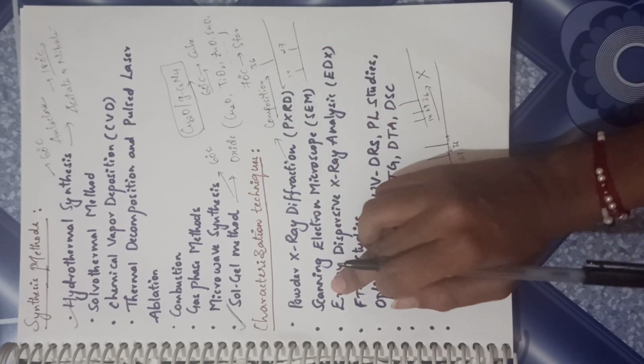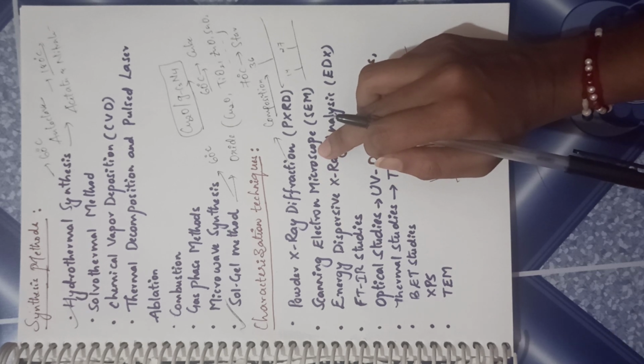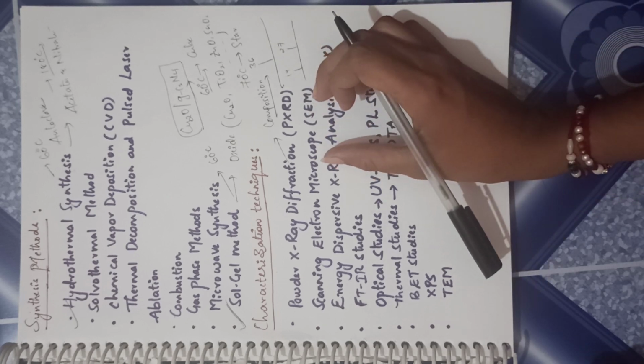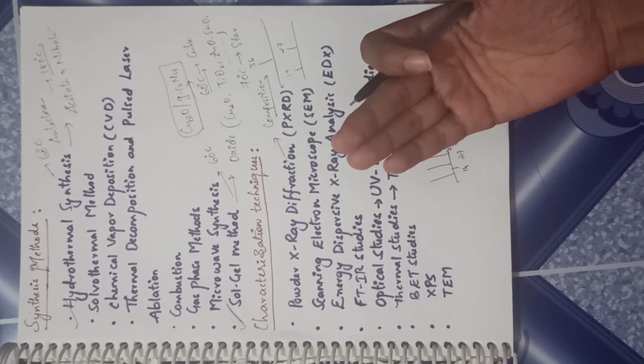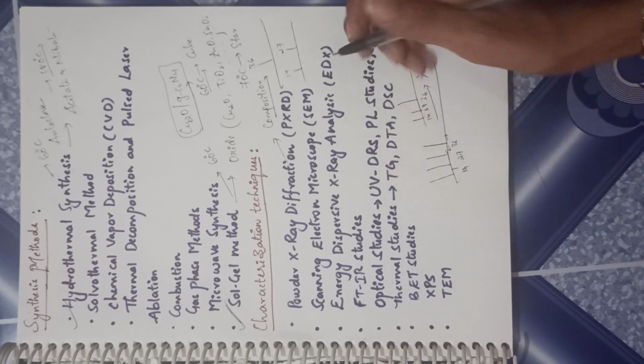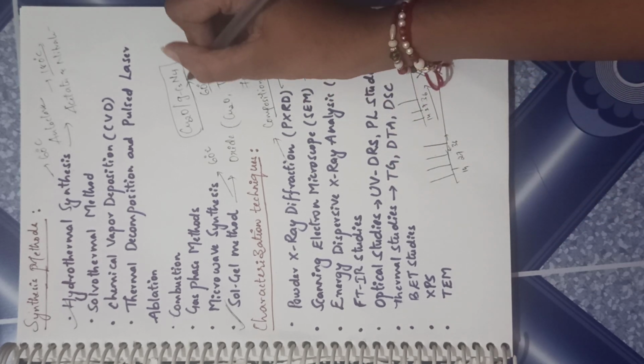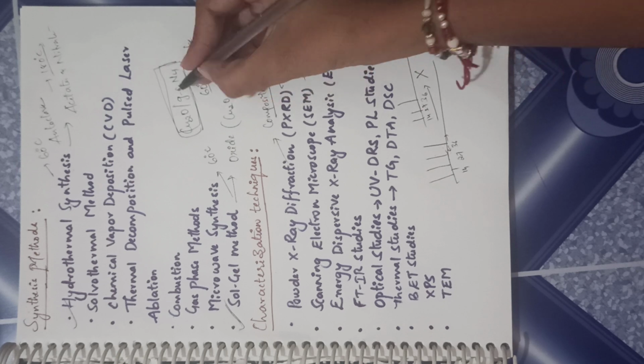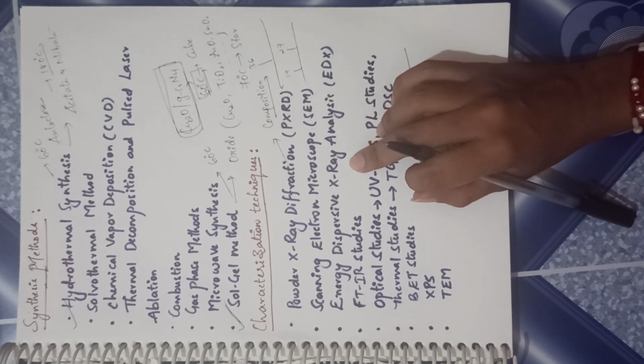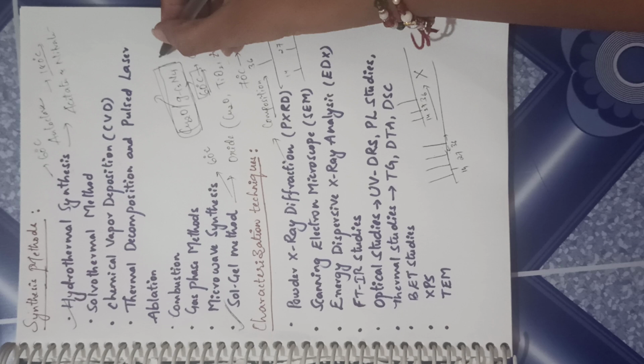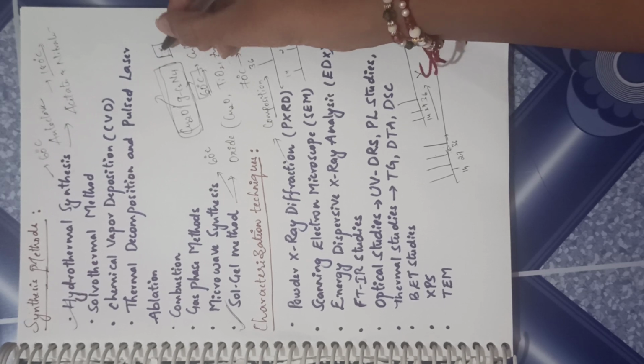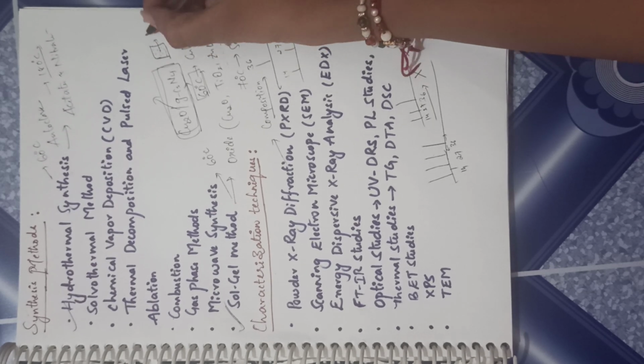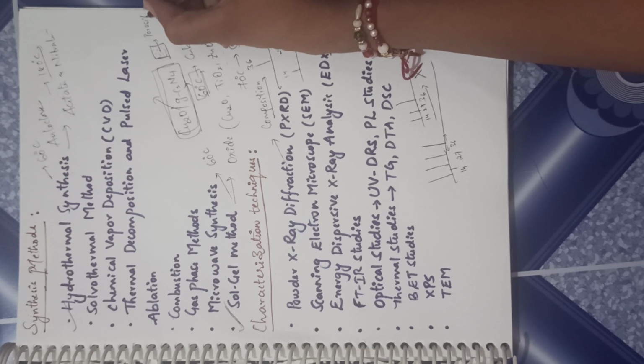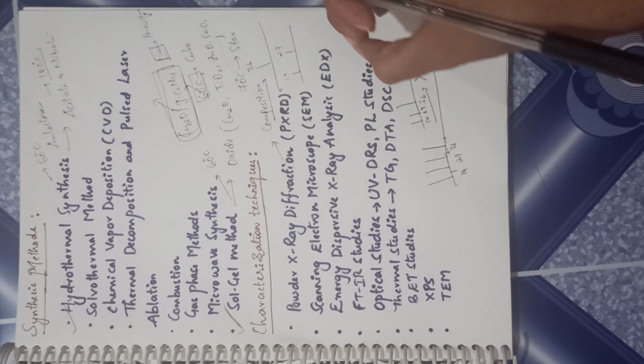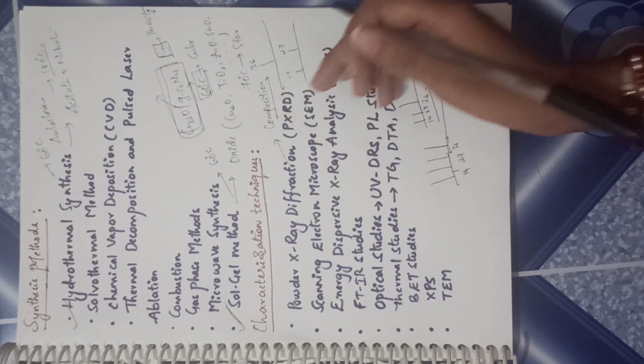that is scanning electron microscope, SEM studies will tell you about the morphology. So in the SEM, it creates an image by detecting reflected or knocked off electrons. So as I told, this particular material I have synthesized at 60 degrees Celsius, and from the SEM studies I have come to know that this material is in the form of cube with some dots on it. Now these dots mean porosity. The porosity in the material is being confirmed.